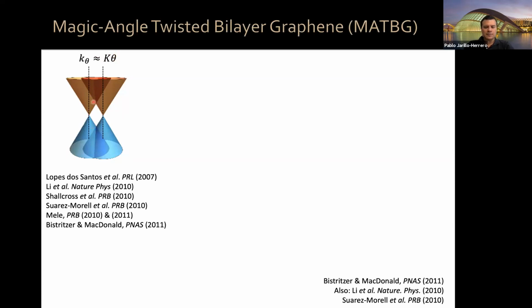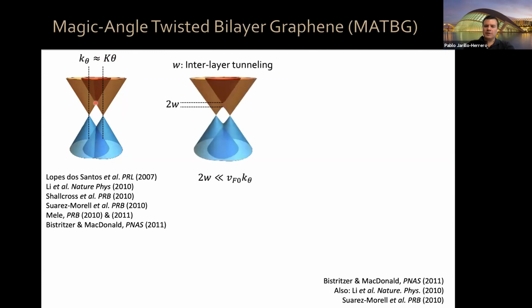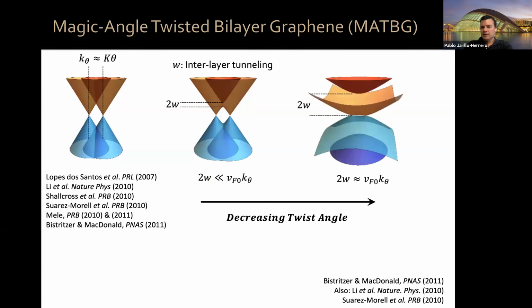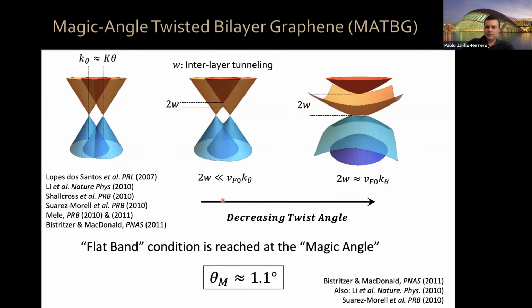And this would be the situation that would occur if electrons in the two graphene sheets didn't know about the other graphene sheet. However, because the two graphene sheets are only 3 angstroms apart, electrons can tunnel between these sheets, and this interlayer tunneling gives rise to bonding and anti-bonding states, okay? Very similar to a hydrogen molecule, but it's now a giant graphene molecule, okay? And this is the situation when this interlayer tunneling is small compared to the energy of this crossing point. But as you decrease the twist angle, the energy of these bonding states goes to lower and lower energy until it reaches 0, okay? That flat band condition is reached at the magic angle, which is 1.1 degrees for magic angle graphene.